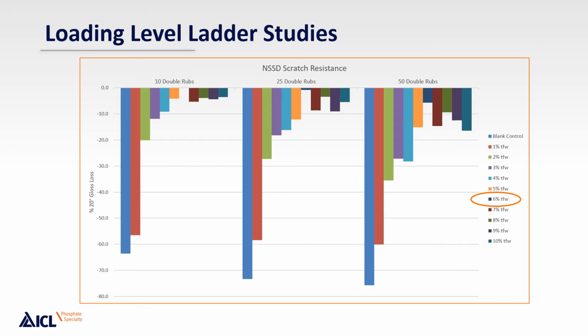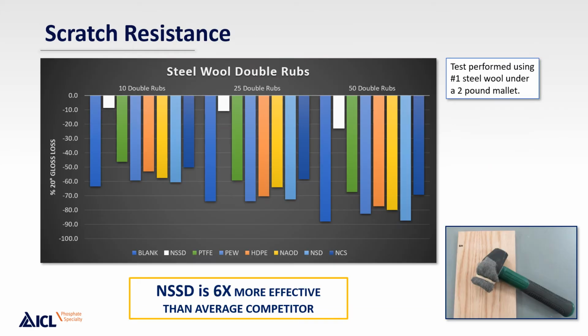For the NSSD in particular, we ran a wider range of performance ladder, and in this case the optimal level was found to be at 6%. There is quite a significant improvement even with a 2% level, but again, we chose the highest level of scratch performance that could be achieved for each of the additives.